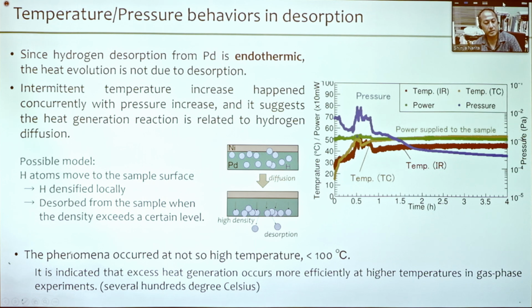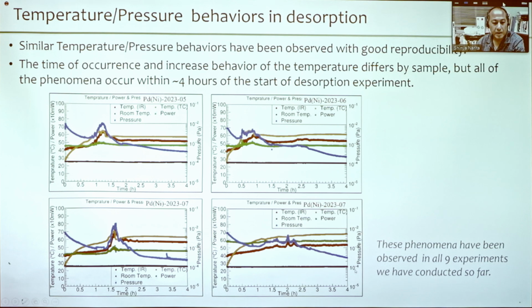But then another notable aspect of this result is that this phenomenon occurred at not so high temperature. It happened below 100 degrees Celsius. So it has been indicated by other experiments in gas phase that excess heat generation occurs more efficiently at higher temperature. In such experiments, excess heat has been observed at several hundred degrees Celsius. So comparing that, in our case, the temperature increase happened at a relatively lower temperature.